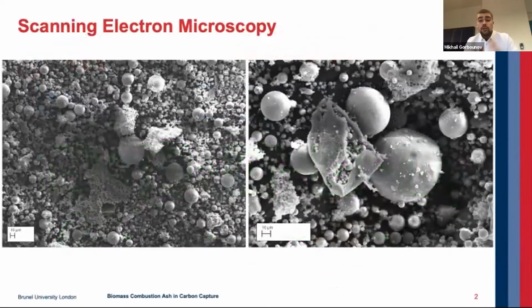The surface morphology of the raw fly ash has been evaluated using scanning electron microscopy, SEM. Given the nature of biomass, i.e. non-conductive, the samples were modified prior to analysis, which involved putting the sample on a conductive silver paste on the sample stub, followed by a deposition of a thin layer of gold coating via the gold sputtering technique. The silver paste, though, can be substituted with carbon tape, but as the investigated material might have carbon in it, we decided to abstain from employing it.